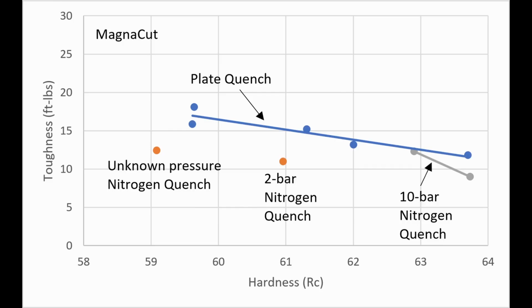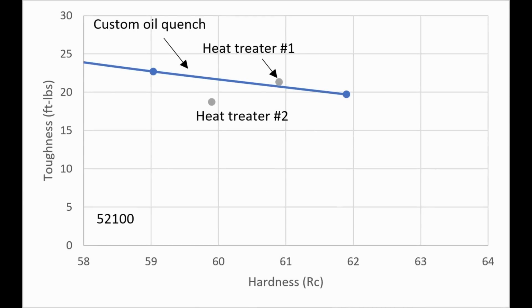The faster 10-bar quench also used a higher austenitizing temperature and a higher target hardness, so the faster quench is not the only reason for higher hardness. However, for a given hardness, this heat treatment was closer in toughness to the custom heat treatment using a relatively rapid plate quench. For carbon and low alloy steels, there aren't as many heat treaters that can handle these steels.